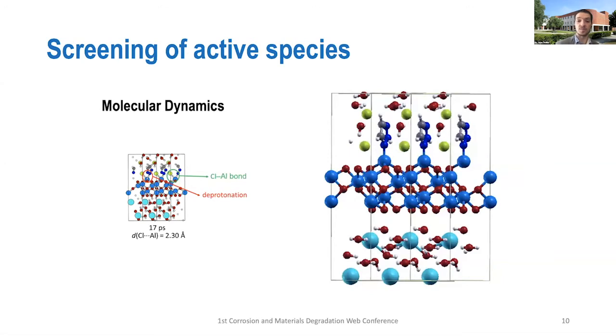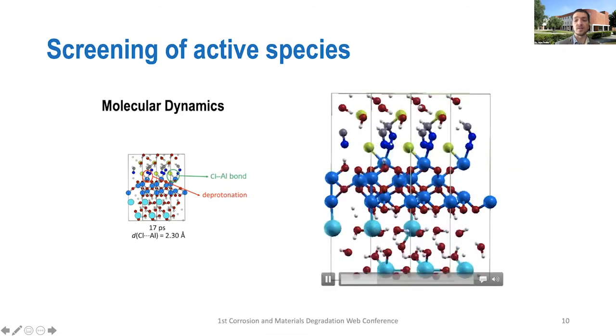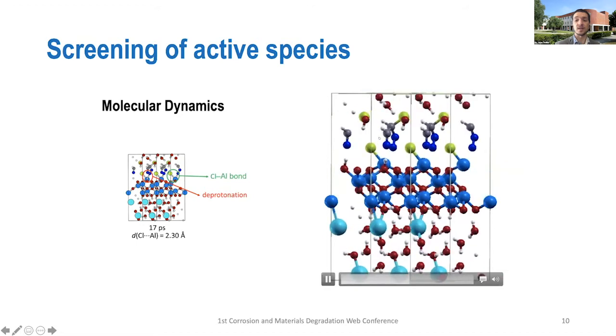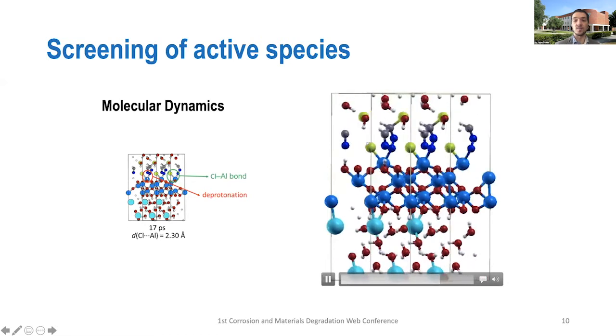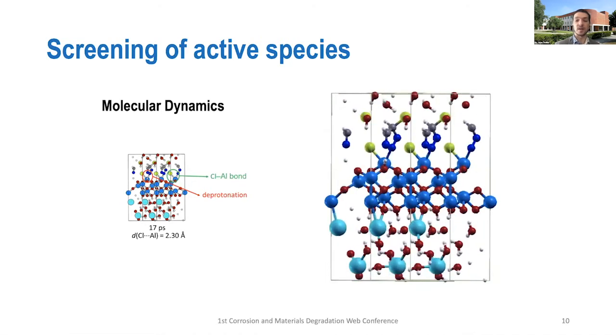So another possibility is actually to use molecular dynamics, and we can use ab initio molecular dynamics to, in addition to the adsorption energy, so the stability of the interaction, get some information on the dynamics of the interaction. Here I'm showing an example of a triazole isomer interacting with the surface, and we can see that in the presence of chlorides there is a competitive adsorption, and we can use this sort of models for very short time frames to understand a bit of this interaction, and even realize that, for instance, in this case, this compound that was being used, this isomer of triazole, was not very efficient from the experimental data that we obtained, and we could somehow understand this lower inhibition efficiency with this competitive adsorption, with the chlorides on the surface. So we can use the computational tools not only to obtain information on the stability, but also on the dynamics of interaction.